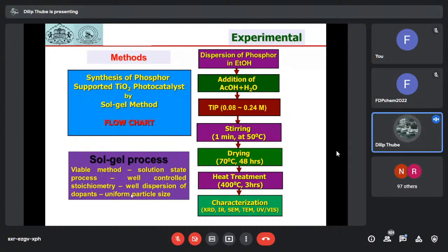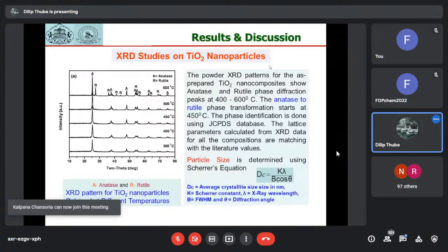This slide shows the experimental method for the preparation of this nano TiO2 material. The phosphor material is dispersed in ethanol, and acidic conditions are maintained by use of a solution of acetic acid, and then the precursor material, titanium isopropoxide, is added in variable quantities. Along with stirring, TiO2 nanoparticles are obtained, which are dried at about 70 degrees Celsius for about 48 hours, and then subjected to heat treatment at about 400 degrees Celsius for 3 hours, as well as 500 and 600. The reaction conditions are optimized, and the obtained materials were characterized using different techniques. The results obtained have been presented here as well as analyzed.